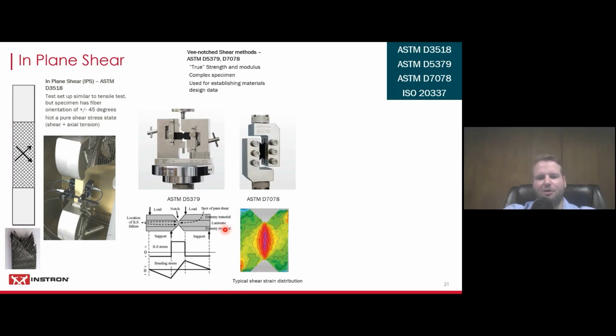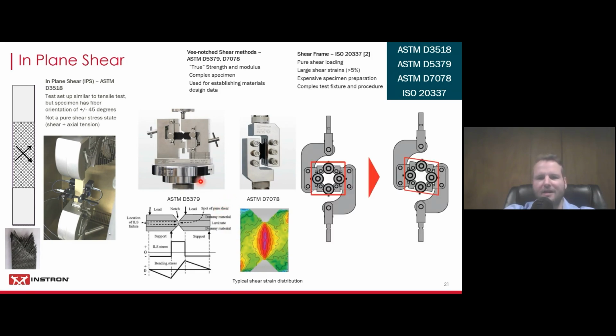And you can see a typical shear strain distribution recorded with digital image correlation. If you have very large shear strains, then you could utilize the test method ISO 20337, which allows you to test the shear properties of specimens that have larger shear strains above 5%. These test methods typically can't provide that, so you would need to use this one, which again is an expensive specimen preparation. And it's a really complex test and a complex fixture. So I would say nothing in composite testing is really straightforward compared to traditional testing.